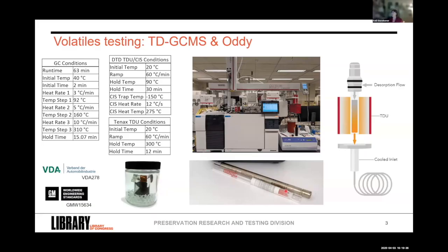Those material samples get introduced into the thermal absorption unit, so a little red box here for us. Heat up to 90 C so that any volatile components that might come off over the lifetime of the material get off-gassed, collected onto the inlet, and then at the end of that 30-minute absorption period, introduced to the GCMS, where they're separated into their individual chemical components, and the mass spectrometer allows us to identify them, and we are semi-quantitative, getting the relative concentrations of each of these different components.